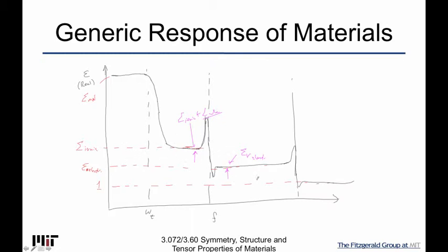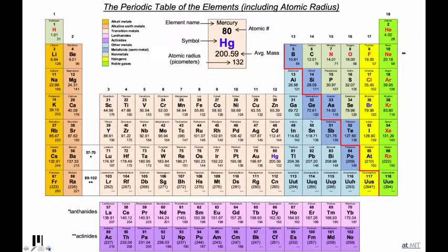And from all this, I can use the Clausius-Mossotti relation to extract the volume per dipole, which I can use, and I can do that over a couple of different material systems, get an idea how it changes with valence and things like that. And in so doing, I can finally populate this thing after a lot of hard work with people long forgotten. I can come in here, and the atomic radius is given here.